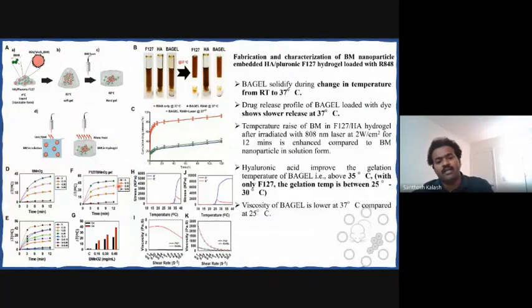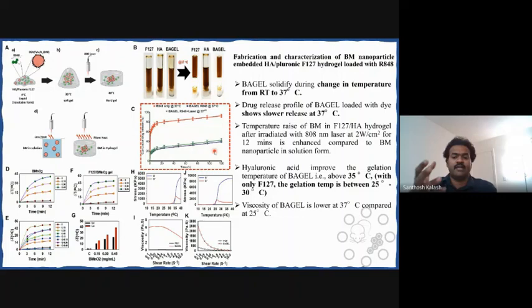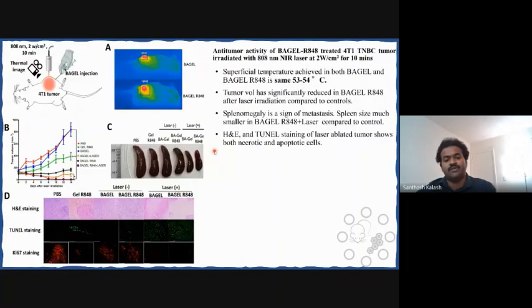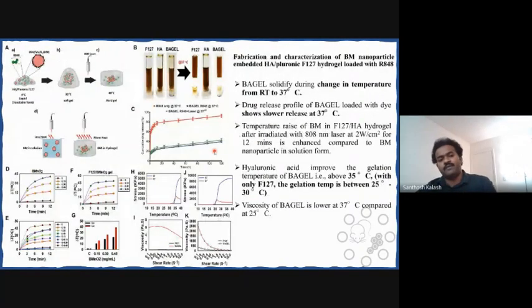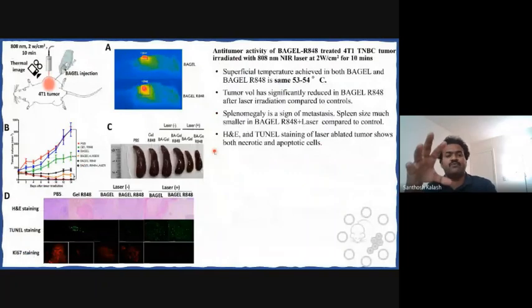And more important is that due to this hydrogel, the drug is not released pretty fast. You can see that the release of the bare drug is pretty fast, but when you use the hydrogel formulations, 20% of the drug is still retained after 5 days of incubation. Which means that they keep the drug for a longer duration compared to free drug administration.